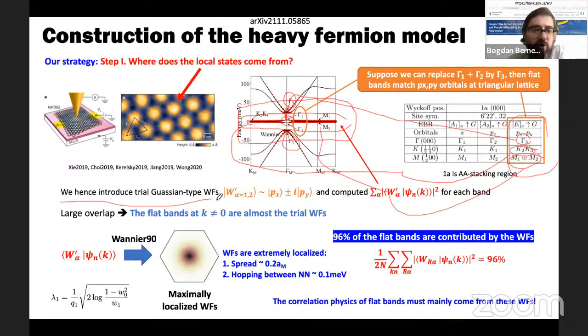So we choose trial Gaussian type wave functions, px plus i py, introduce them into Wannier 90 with the Bistritzer-MacDonald band structure, perform maximally localized Wannier states, and obtain the following result. Obtain Wannier states that are localized within 0.2 of the Moiré lattice, so extremely localized. You can see how these look very similar. And the hopping between them is 0.1 milli-electron volts, so very small. So these are very localized states.